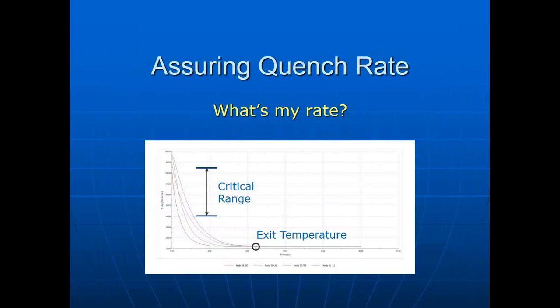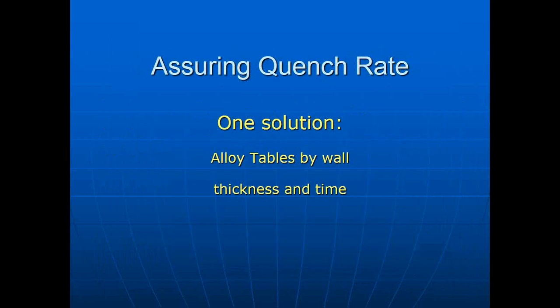My recommendation, one way to define rates is to create an alloy table. This is specific to one particular press line, one particular quench, because the performance of that quench will dictate the chart. But we can experimentally lay out an alloy table by wall thickness and time, and then the operators can use that as the assurance tool. If you're meeting the wall thickness and time specifications, you will assure your product performance at the quench.